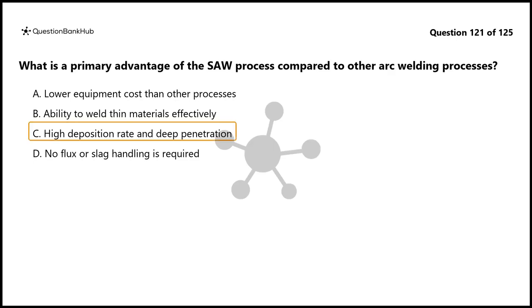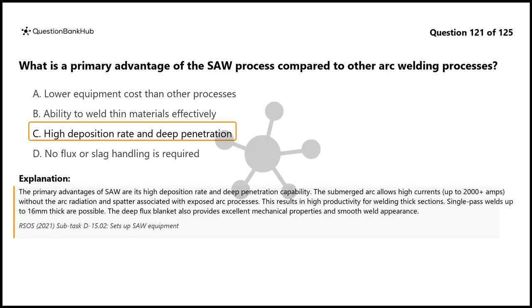The correct answer is C. High deposition rate and deep penetration. The primary advantages of SAW are its high deposition rate and deep penetration capability. The submerged arc allows high currents, up to 2000 plus amps, without the arc radiation and spatter associated with exposed arc processes. This results in high productivity for welding thick sections.